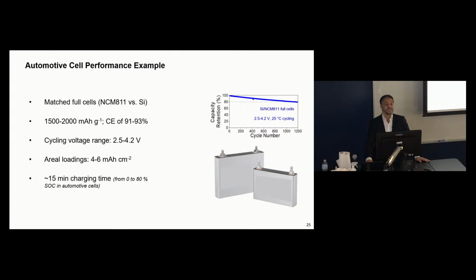And so, in fact, with silicon, because the anodes are thinner compared to graphite, and the charging time is related to diffusion of lithium ions through the electrode thickness, the thinner the anode, the faster you can charge, right? And so we can enable fast charging almost effectively for free. In conventional batteries, if you want to develop fast charging, you have to sacrifice something. Typically, people sacrifice energy density and cost. If you want fast charging, the batteries become more expensive, right? And the vehicles will be able to drive shorter distances.